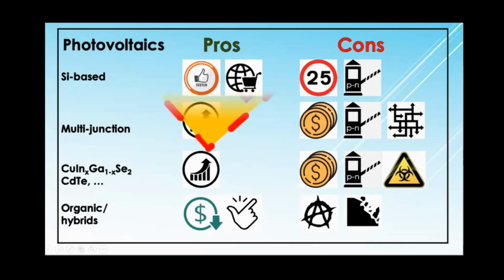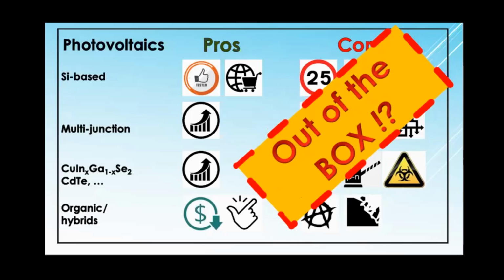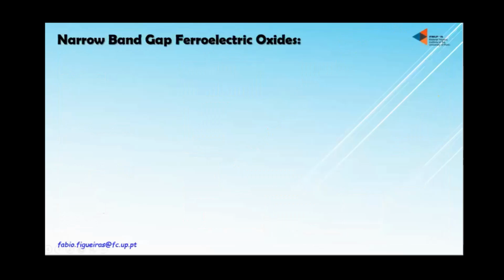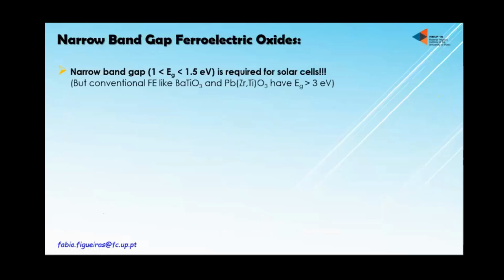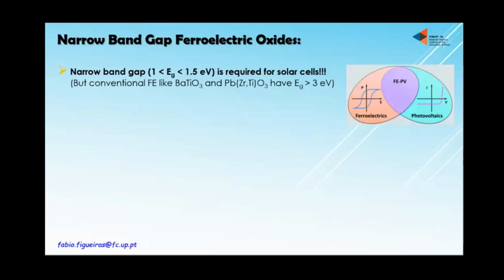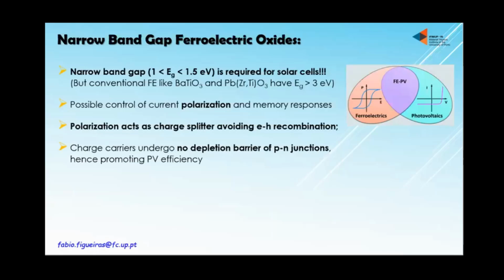So my point is to go out of the box of these traditional materials. Organic and inorganic hybrids are not traditional, but they have limitations. So where do I go now? My proposal is to find an oxide with a narrow band gap that will replace silicon. But most oxides, especially ferroelectric oxides, will have a very high band gap. So I need that material to use ferroelectricity instead of a p-n junction. A p-n junction provides an electric field that separates electrons from holes from the photogeneration. So if I use the electric field from polarization, I can avoid the p-n junction.